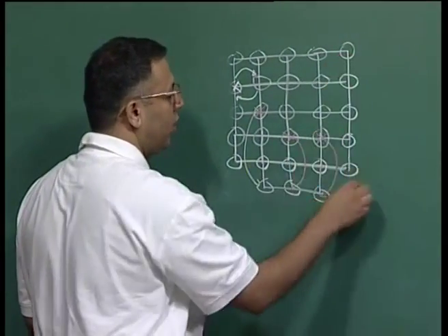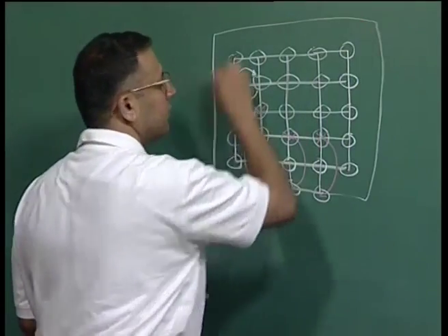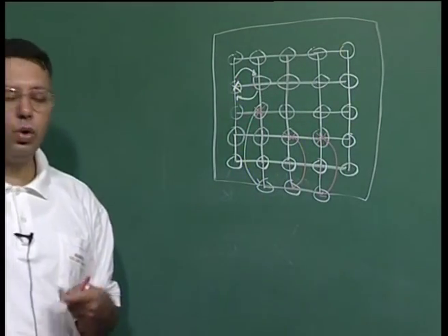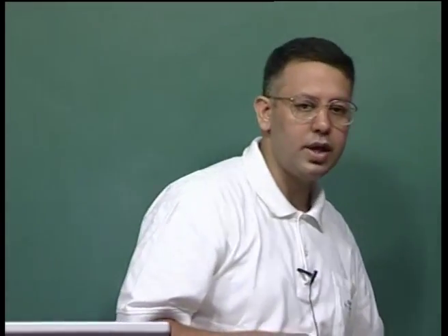If this happened in all 3 dimensions, my crystal would become larger with heating. Though, as you can see, it is a 1 in 10,000 effect, and with respect to normal thermal expansion it has a very small fractional contribution, still, purely because of entropy, the system is now expanding.